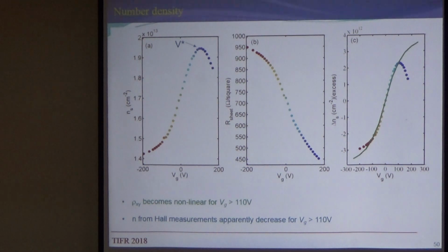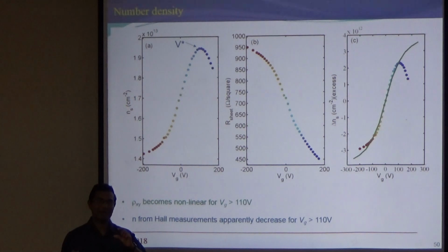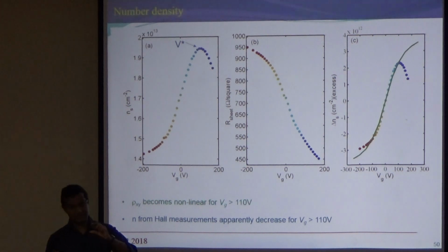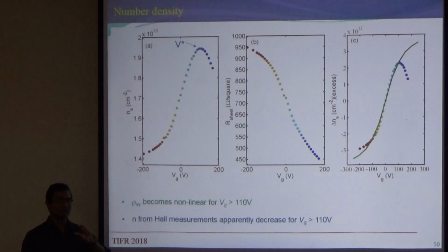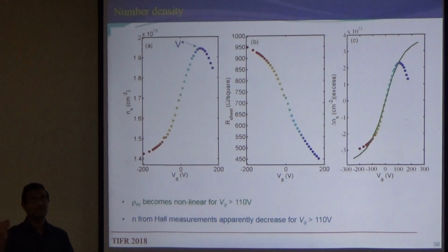So, what is the multiband transition? Here, that is the multiband transition. So, now you can take the dielectric. As I told you, strontium titanate is a quantum paraelectric, which means its capacitance depends very strongly on the electric field. Capacitance is epsilon naught epsilon r by d per unit area, but this epsilon r is a very strong function of gate voltage.